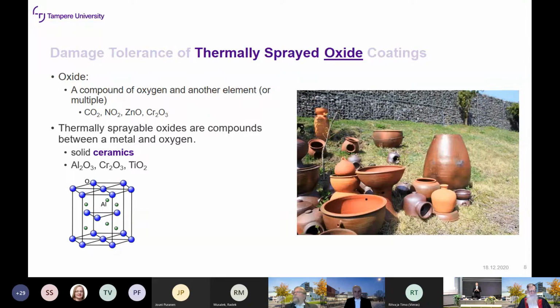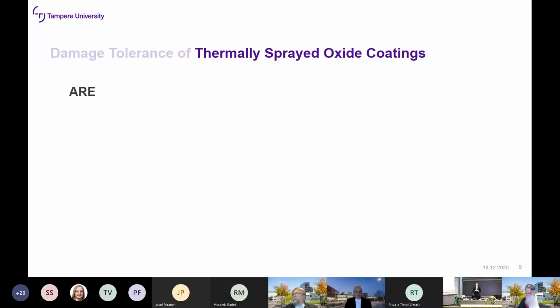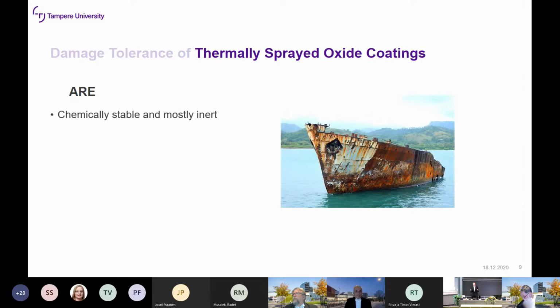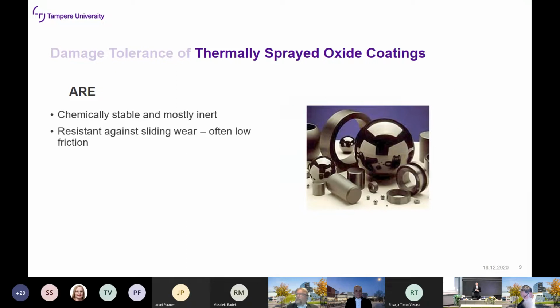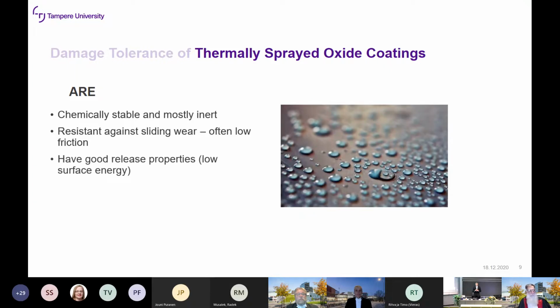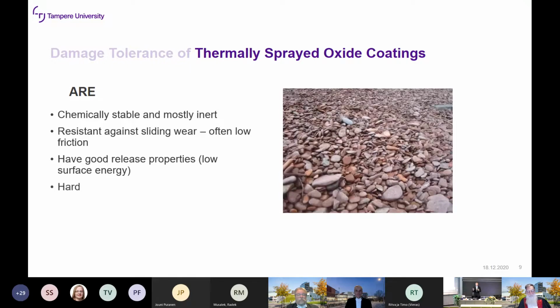Possibly the most used is zirconium oxide, but any oxide pretty much could be sprayed. And it can come in almost all feedstock forms, not wire, because ceramics are difficult to make a wire from. Now, thermally sprayed oxide coatings, what are they? They are chemically stable for corrosion protection if they're dense. They resist sliding wear, also other types of wear, but really against sliding wear, they're really good. And they have good release properties where that's needed, low surface energy, and they're hard.